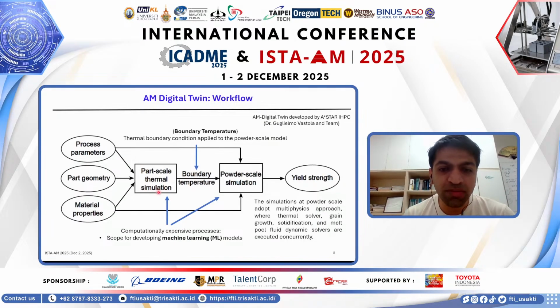And then from this part scale simulation, we take one single metric that describes the thermal history that has been experienced by the whole part, and that metric is called boundary temperature. And we then use this boundary temperature as an important boundary condition in the powder scale simulations when we do a multi-scale simulation of the powder bed fusion process, including the melt pool, the grain growth, the solidification of the melt pool, and so on.